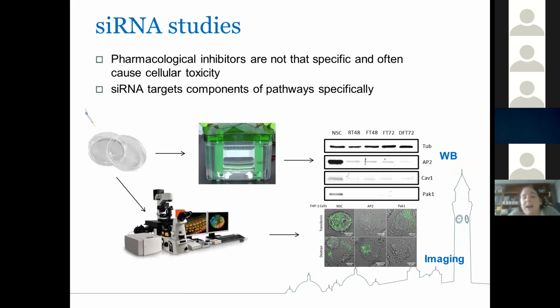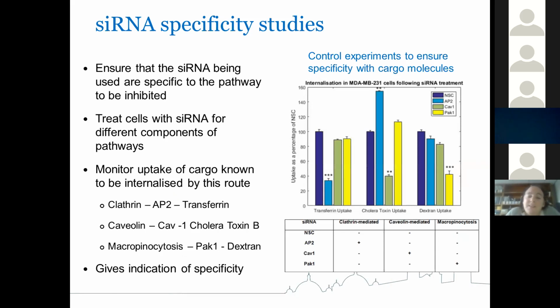So in each case, we compared pharmacological inhibitors and the siRNA, the silencing RNA, to target the specific pathways. We confirmed through Western blotting that we had indeed knocked out the relevant proteins, that they weren't being expressed anymore. And then we correlated that with the amount of particles that were taken up in each of the knockdown cells to understand the amount of uptake and which pathway was involved. So it's quite well known that siRNA is much more specific than the pharmacological inhibitors. So we were hoping that we would really be able to pinpoint which receptor-mediated process was used. And as I said, we confirmed that the silencing RNA used did inhibit the specific uptake.